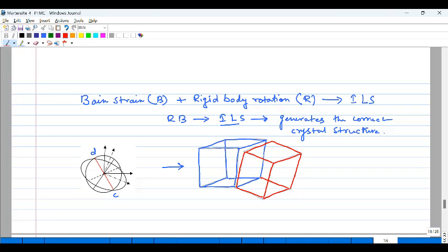Okay, so here you can see that the strain which transforms austenite into martensite is an invariant line strain where one line at the interface remains unchanged. So this is the line over here that you can see. This line remains undistorted. Okay. So this is an ILS, this is an invariant line strain. But what actually is observed, as I said before, is an invariant plane strain. Okay.